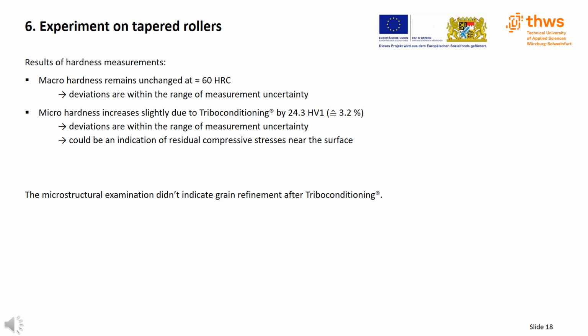Following the microstructural examination, there was no indication of grain refinement due to triboconditioning. The Standard and Tribonex tapered rollers had a homogeneous martensitic microstructure with iron chromium carbides.